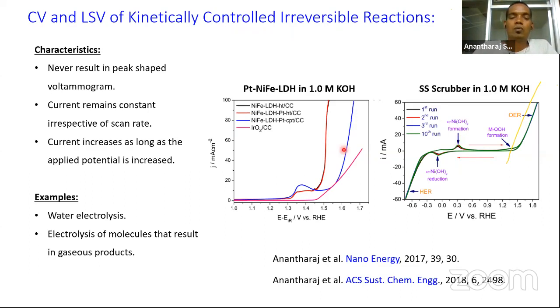So in this case, the product which is formed here is nothing but the oxygen gas, and the product that is formed here is nothing but the hydrogen gas. Once the product is formed, it escapes out of the solution from the electrode surface, which means that there is no practical concentration gradient occurring, which means that there is no diffusion layer formation. When there is no diffusion layer formation, the current will be totally controlled by the concentration of the electroactive species on the electrode surface, which is not changing practically.